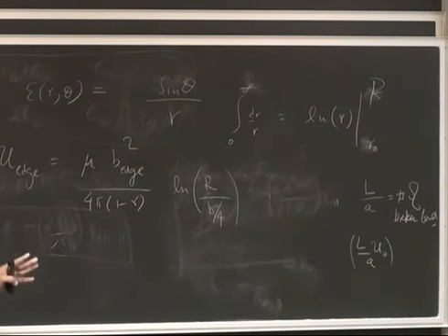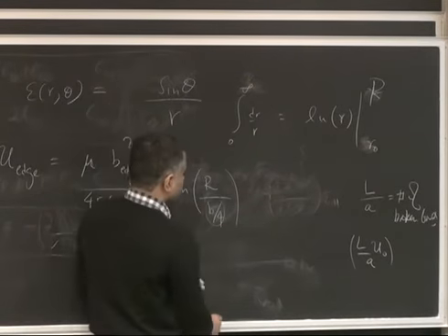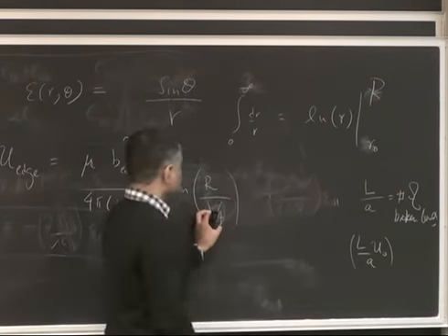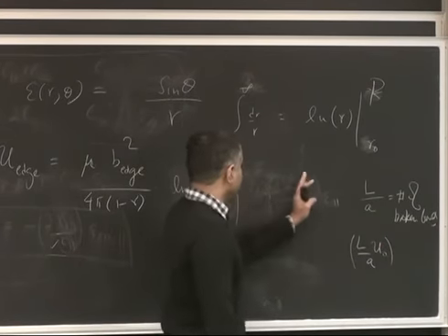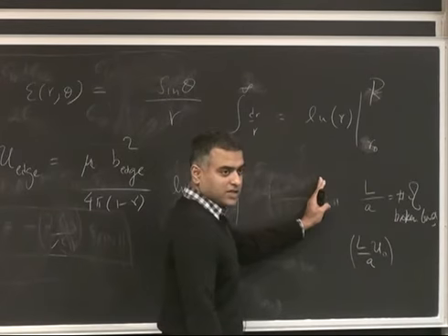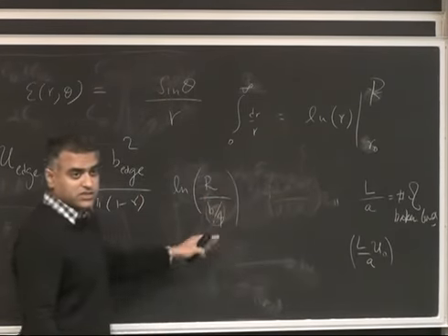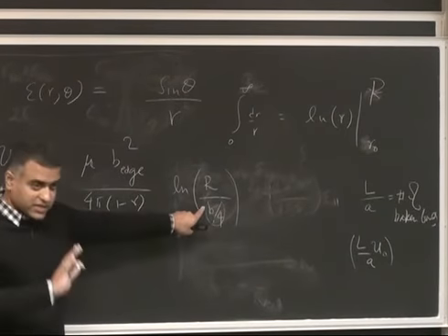Does that make sense, what I'm doing? So if, instead of the lower limit being 0 or some arbitrary number, or one lattice constant, I take 1/4 of the lattice constant, it also accounts for this energy scale. Because in the end, it will be plus something else, or minus something else, and you can absorb it in the natural log here, right? Empirically, it's found that if you take 1/4 of the Burgers vector, it accounts for that.